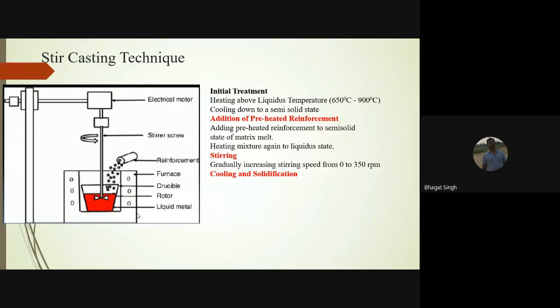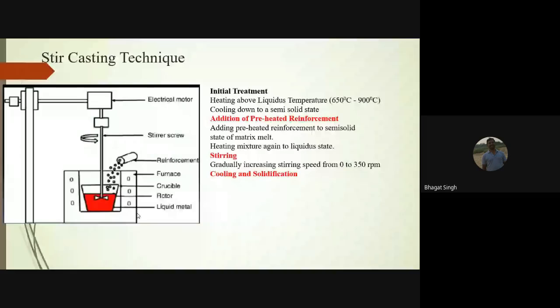So what is the need for the preheating? Generally, if you add this basalt powder directly into the molten metal, it will not act as a nucleation agent. The nucleation agent is one of the primary mechanisms responsible for grain refinement. The grain refinement occurs during the solidification. As a result, the strength improves.